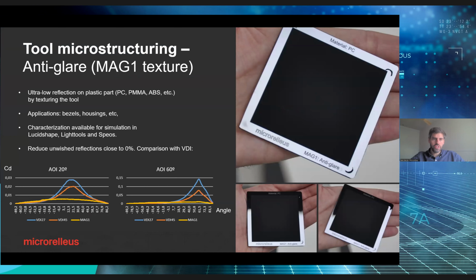In this case, for example, anti-glare. So we have ultra low reflection on the plastic injected part that can be PC, PMMA, ABS, etc., just by texturing the tool. Applications: bezels, housings, etc. Any part where you want to avoid reflection. Here we can see an image comparing the reflection of our anti-glare texture with standard VDI textures in the market. As you can see, the difference is really, really huge.